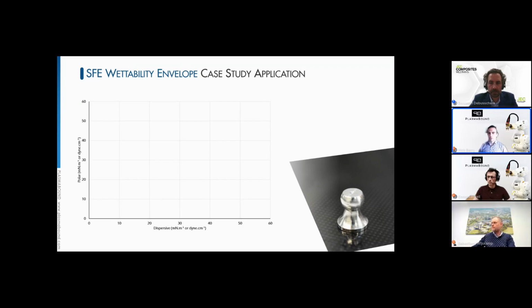So they came to us with this virgin surface. So we evaluated the surface-free energy and generated this wettability envelope. Using the customer's current preparation technique, we built the benchmark, which is what we have to compete with. And then when we evaluated their adhesive, we found the surface tension to exist out here. So immediately we understood the problem that we were trying to deal with. We engaged the customer, and the customer did agree with us. They were having intermittent issues where good bonding and sometimes not so good bonding was occurring. So this explained why they approached us, and we understood the situation.